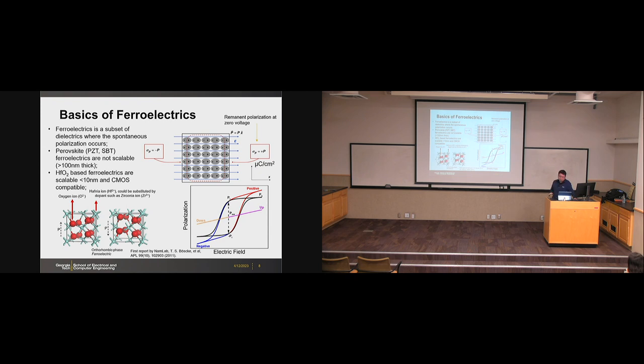So this is the basics for the ferroelectrics, and the ferroelectrics is not new, as it was discovered more than 100 years ago. But historically, most of the ferroelectric material is based on those perovskite materials like PZT, SBT, very complex oxides. And those ferroelectrics are not scalable, so the thickness needs to be larger than 100 nanometers. So it's not very scalable to today's advanced CMOS technology.